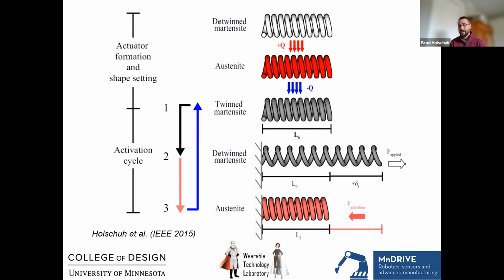And then we have a linear actuator, which in cold state can be deformed. You can take the spring and you can extend it and it will stay extended. And then when you heat it up, either using direct heating or using joule heating with an applied current, you can create linear actuation. So that spring, which has been overextended, can then recoil and produce a linear displacement or a linear pulling force or a tension or a pressure or whatever it is that you want to generate.